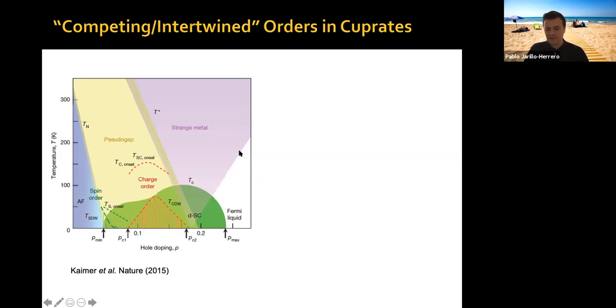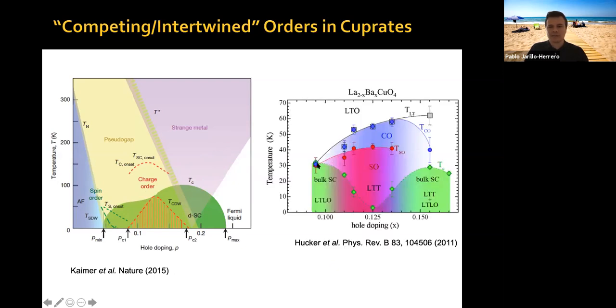Now, this is for a given cuprate. Cuprates are a large family of materials. So for some materials, Tc goes almost all the way to zero at that 1/8 doping. This depression of Tc has long been argued, and I think there is quite strong evidence, to be related to another competing order. It can be stripes, it can be charge density waves, various types of charge order, which compete with superconductivity and hence depress Tc for this particular doping.